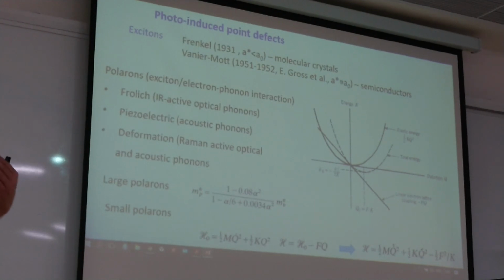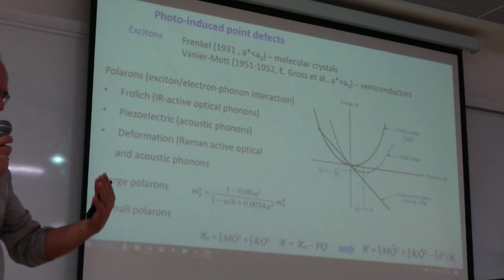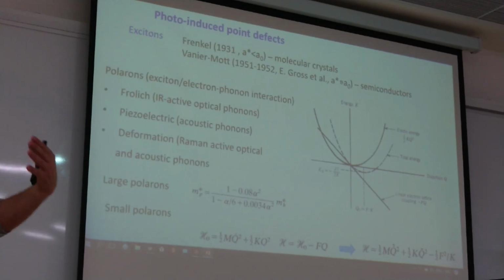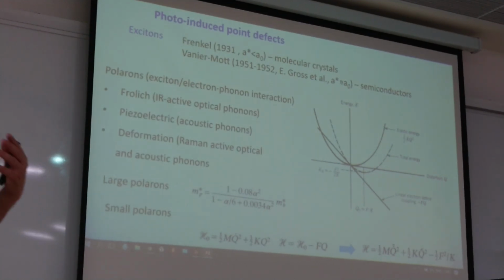To change the crystalline lattice by electrons, we should consider electron-phonon interaction or exciton-phonon interaction. Phonon is the lattice vibration, and if we make this lattice vibration very strong at a specific point, we can change the structure. So these kind of interactions are called polarons. And interactions which can occur between electrons or excitons and lattice are divided into a few cases. Fröhlich interaction, which is interaction with infrared active optical phonons. Piezoelectric interaction with acoustic phonons. And deformation potential interaction, which involves Raman active optical and acoustic phonons.